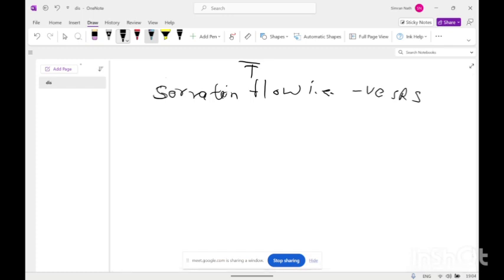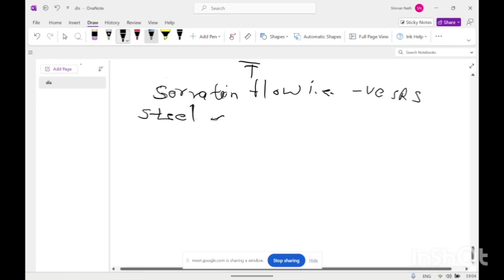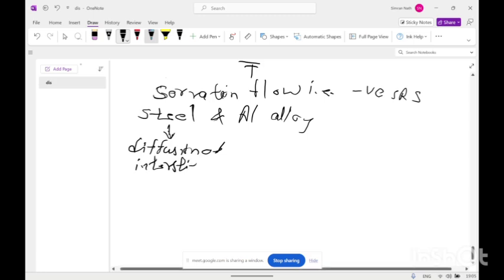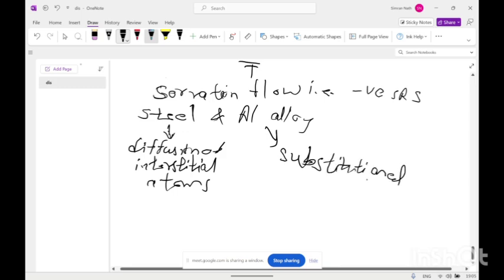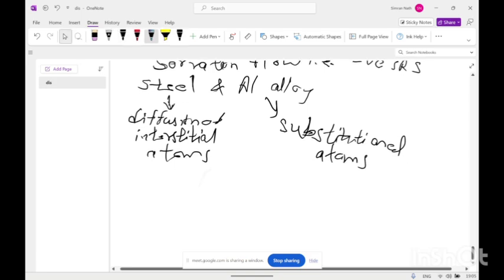So if we compare the dynamic strain aging in steel and aluminum alloys, in steel it is the diffusion of interstitial atoms that resulted in the dynamic strain aging, while for aluminum these are the substitutional atoms. So interstitial atoms can be like carbon and nitrogen atoms in the steel, while for substitutional atoms there is magnesium in the aluminum.